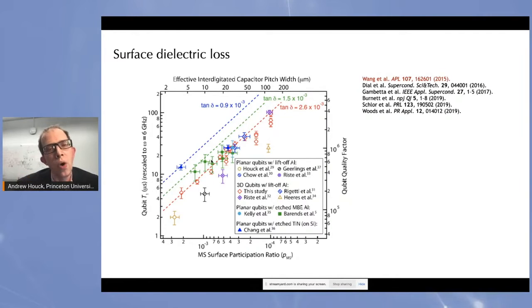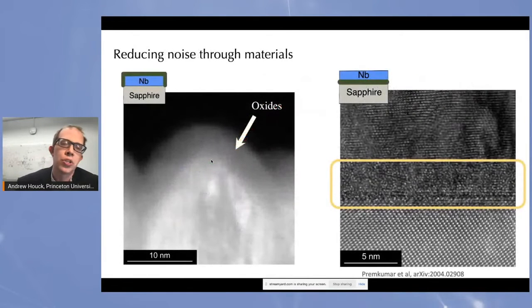What is going on at the surfaces of the metal and of the sapphire that are limiting our problems? Well, you can use the tools of material science to actually take a closer look. So here's a picture of niobium, which is the material that many superconducting qubits are made of. At the surface of it is oxide. This is like the rust that grows on your iron. And it's quite bad for maintaining coherence. And if you look very closely at the interface between the sapphire and the niobium, you can see that there's this sort of garbled mess.